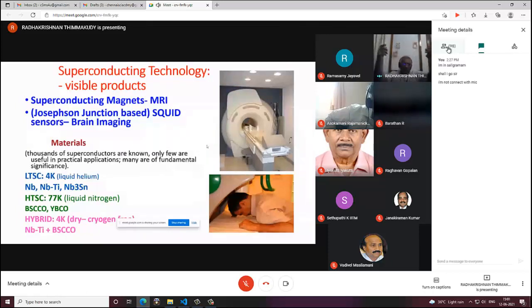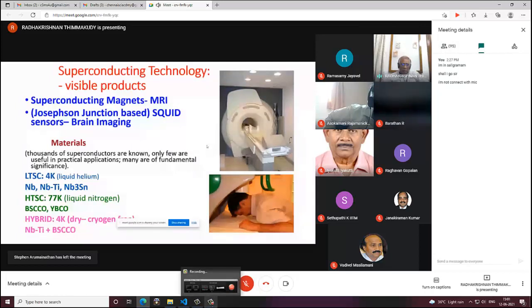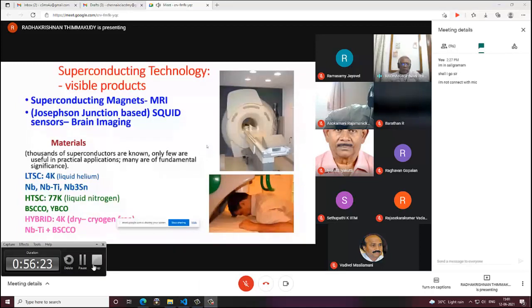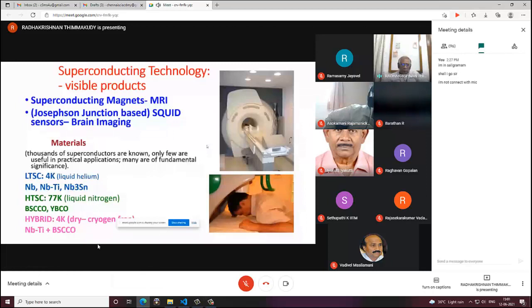So the thermal input from the external atmosphere to the magnet inside the cryostat becomes small, and so the heat input to the refrigerator operating at 4 degrees Kelvin, which is normally an issue, that's why you use liquid helium, is now small. So there is a concept of dry magnets. If you combine the high temperature superconducting leads with low temperature magnetic material, then you can have a dry magnet, that means a cryogen free magnet, but operating at 4 degrees Kelvin. So that kind of thing is there.